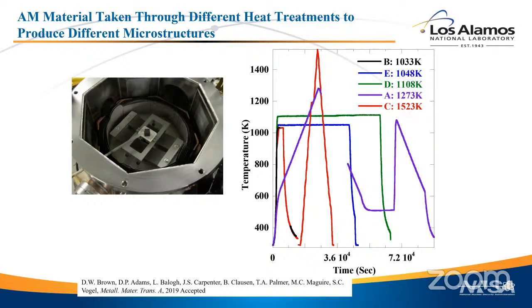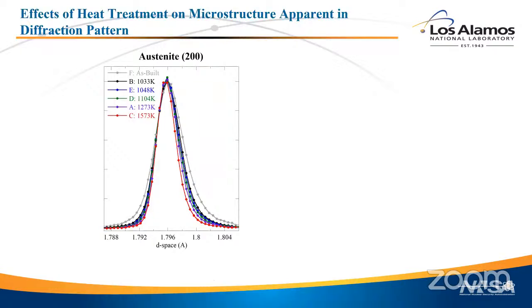So we heated it until we saw one microfeature go away, and then we stopped. And then we tested that material without that microstructure feature. And then we took sample A, for instance, 150 degrees higher. So then we took a different microstructural feature out, and then we tested that material. So by doing it in situ, we could selectively pull out parts of the microstructure and see how that related to the final strength of the material.